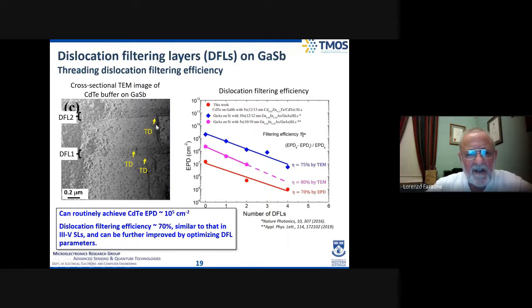You can see evidence here in this electron micrograph of threading dislocations, threading through from the substrate, and when they hit the dislocation filtering layer, they terminate. Similarly, there's another one here that terminates in the filtering layer. You can see the alternating layers of compressive, tensile stressed layers within that dislocation filtering layer.